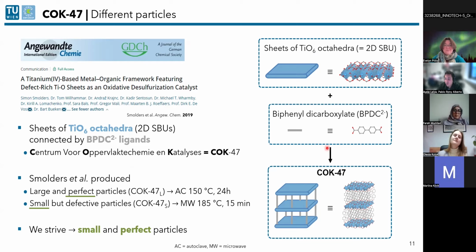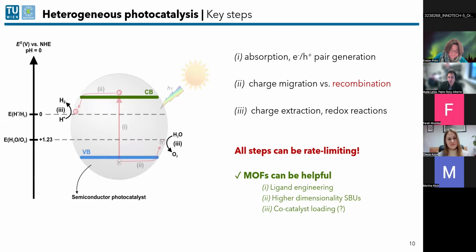What we showed in this work was that actually, in this particular case, I think it's very complicated to have just a one-liner of how to avoid recombination. But in this particular case, we saw that having these missing linker defects in this structure was very detrimental in terms of recombination center. So we also showed this with theory simulations in the main paper. So yeah, as you can imagine, these particles, when the charges are traveling through the SBU to the surface, if you have there some reactive site, some missing linker defect, which is usually capped by methoxy groups, that might be a recombination center. So what we did was we tried to make these particles very less defective and also very small, because then the distance that these charges have to travel is also lower, and there is just more probability that they will make it to the surface. Yeah, so I think that was our strategy here. There might be others.